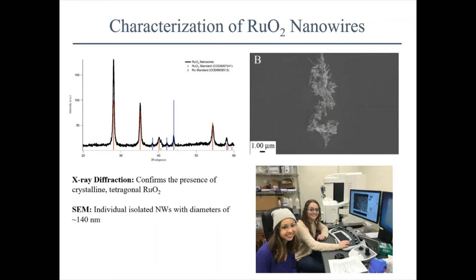We also have access to scanning electron microscopy at Fordham, and in this case, we were able to observe that the wires were nice individually isolated nanowires with fairly large lengths and good aspect ratios, and the diameter of the wires was 140 nanometers.